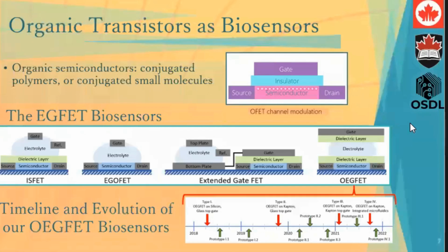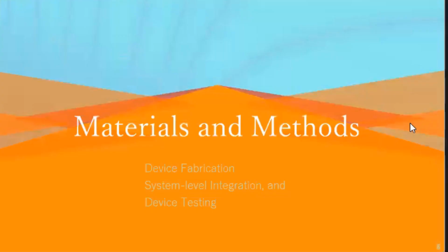And the bottom dielectric could be a self-assembled monolayer, or it could be a porous layer, allowing minimal interaction with the semiconductor. Our hypothesis was that this will extend the shelf life for continuous health monitoring, because we didn't want it to be essentially disposable for all types of applications. As you can see, we have gradually moved from rigid assembly to soft Kapton and glass top, that was generation 2, to Kapton, but the fluidics integration wasn't there. More recently, within a year and a half, we have done a seamless assembly of soft fluidics. And I'll talk a little bit about that here.